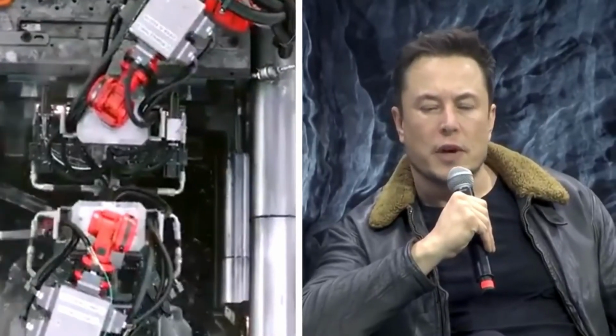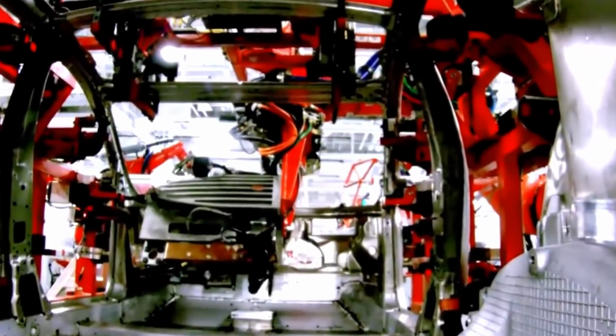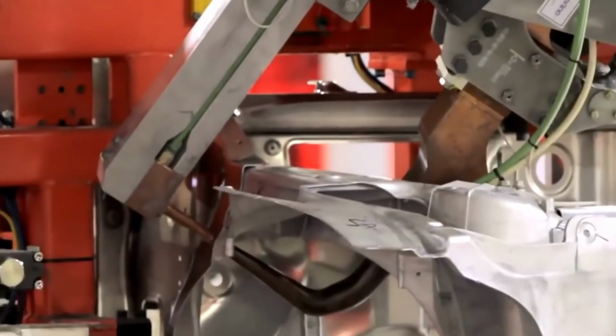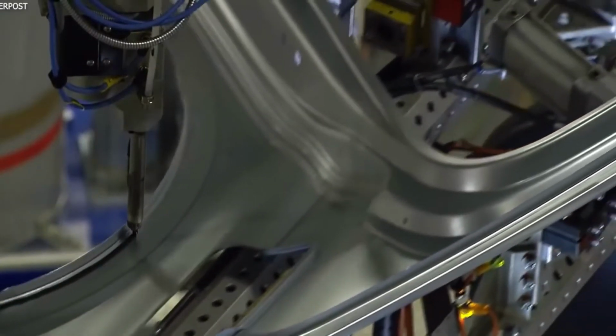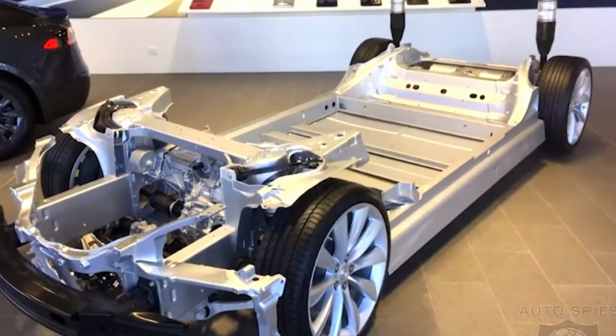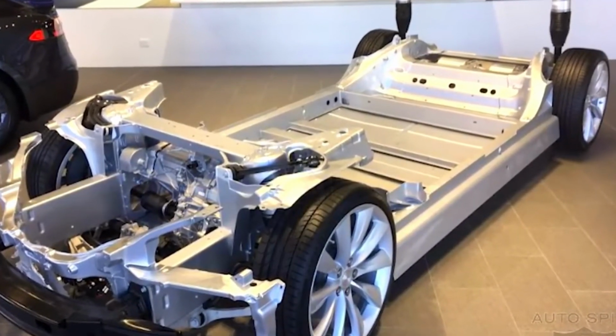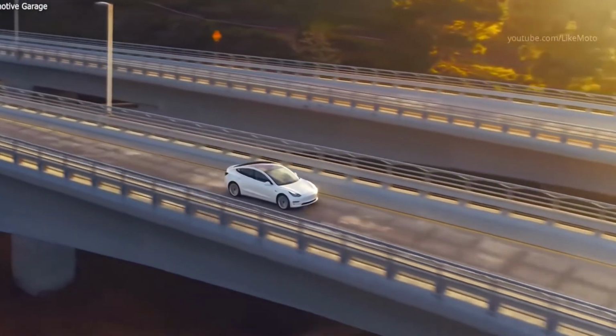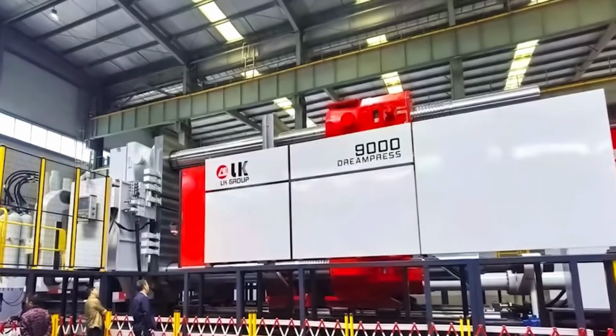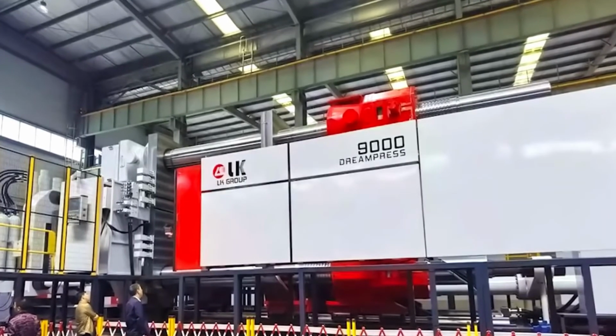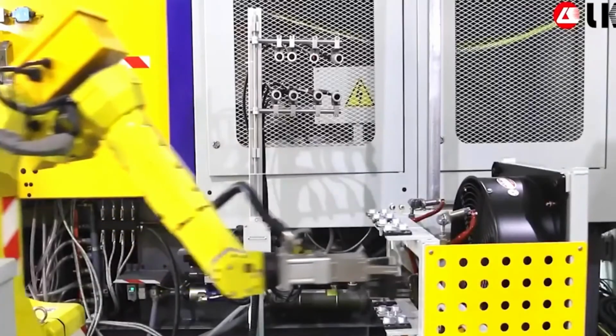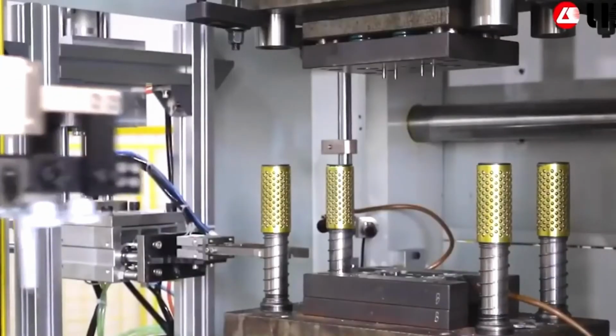A robot reaches in and removes the casting, placing it in a quenching tank to reduce the temperature from 400 to 50 degrees Celsius. A mechanical trim press cuts the approximate edges with excess aluminum being recycled back into the melting oven. The remaining useful part of the casting is X-rayed to check the internal structure, trimmed by laser, drilled for fittings, and then computer measured for accuracy.